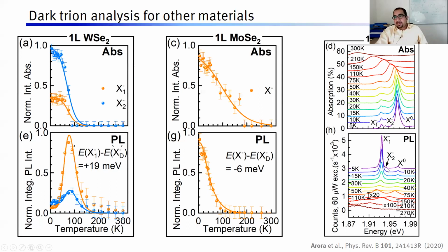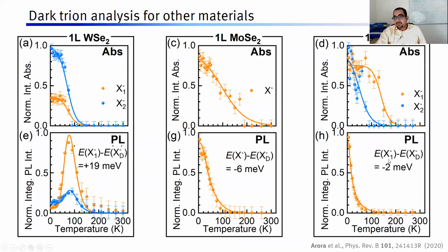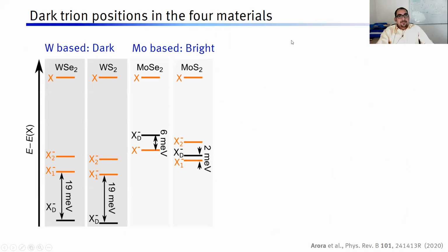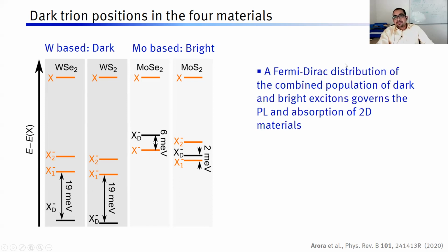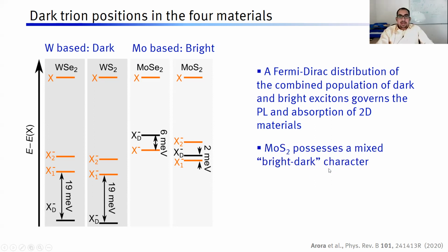For MoS2, it's very complicated. It's almost a mixed state. So within 2 meV, bright and dark trion states lie very close to each other. So summarizing, essentially, we can create a picture here where there are these excitons, and then we can have these trions below the excitons, and the dark trions are the lowest in energy for tungsten diselenide and tungsten disulfide. For MoSe2, the bright trion is lowest in energy, and for MoS2, this is almost like a mixed state. They are very close to each other. So what we prove here is that a Fermi-Dirac distribution of the combined population of dark and bright excitons governs the PL and absorption of two-dimensional materials. MoS2 possesses a mixed bright-dark character.